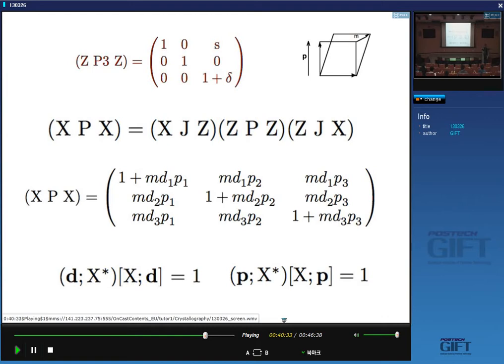We know how the z-axes are related to, say, the crystallographic axes, because z1 might be the shear direction, which is 110. z2 might be, you know, the 111 direction. So we derive the coordinate transformation matrix in the normal way, do a similarity transformation, and I can get my deformation matrix in the crystallographic frame. And I said to you that we can make x anything we want.